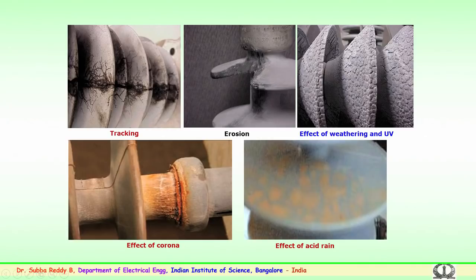This gives the effect of corona over a period of time. You can see the metallic junction to the fiberglass rod. This is a very critical thing which has to be taken care of. Once there are microstructure damages, as mentioned, water, moisture or mist and fog seeping in could lead to brittle fracture. Corrosion happening near the metal end fittings is not a healthy thing, so it has to be properly seen that coatings of the metallic end fittings are done and they are properly protected. Similarly, as discussed, there is the effect of acid rain. Acidic components spread from factories near the transmission system could again lead to surface degradation over a period, and this could damage the insulator in the field.